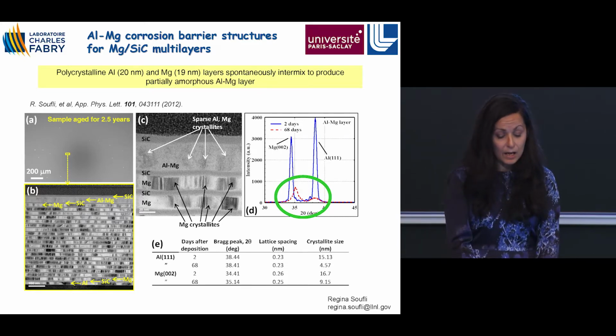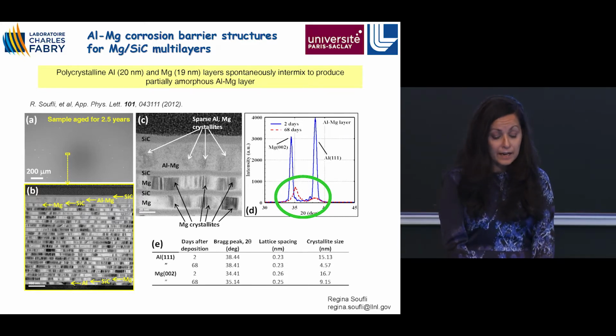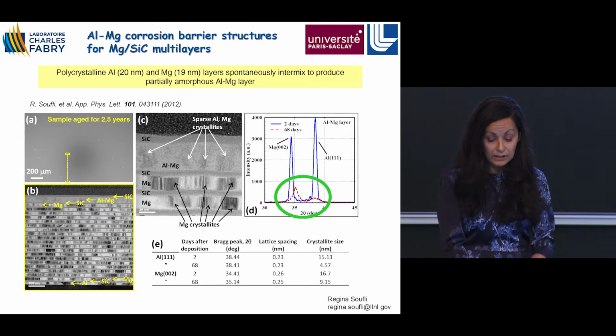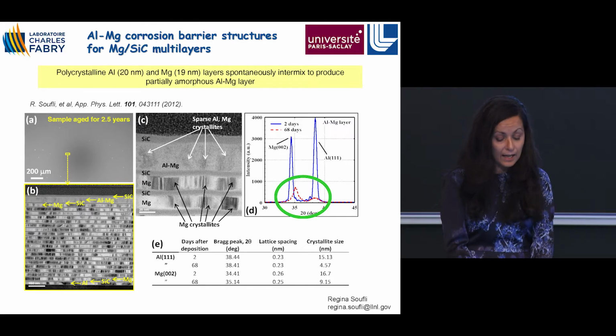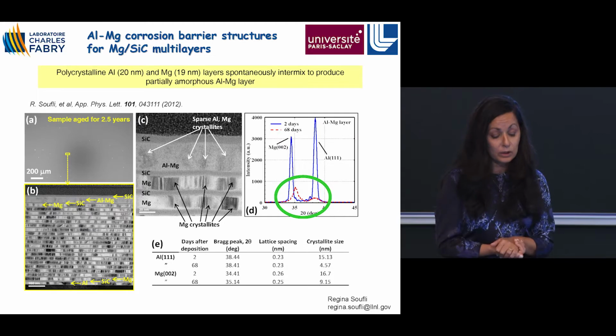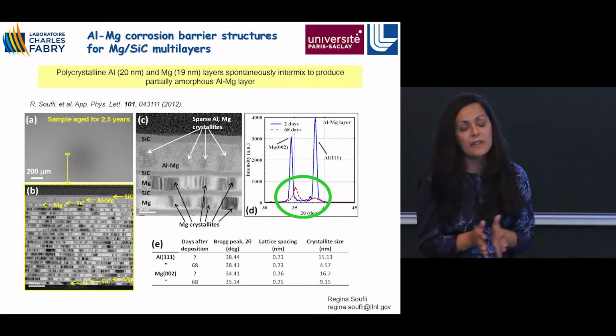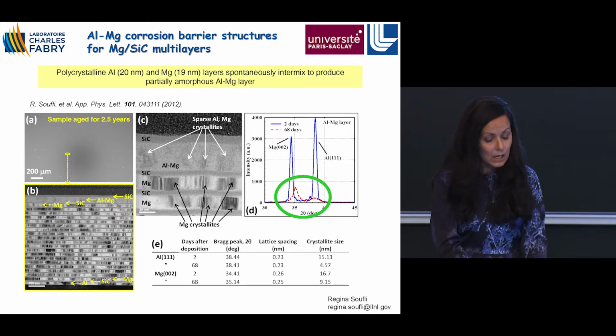You can put this corrosion barrier in one of the magnesium layers, or you can put it in 2 or 3, or in all the layers in the multilayer. It can be underneath the topmost silicon carbide layer, or at the bottom of the multilayer structure, or you can put it in all the magnesium layers with very small penalty in reflectivity. And as you can see here, we have aged this sample for 2.5 years, and there is almost no corrosion.